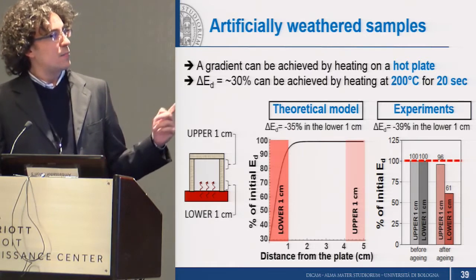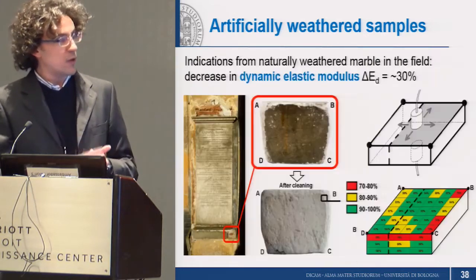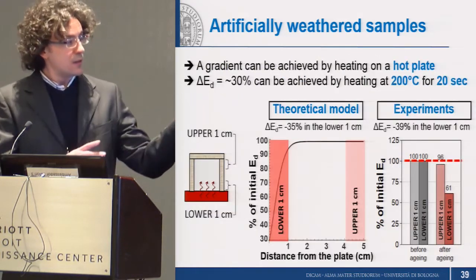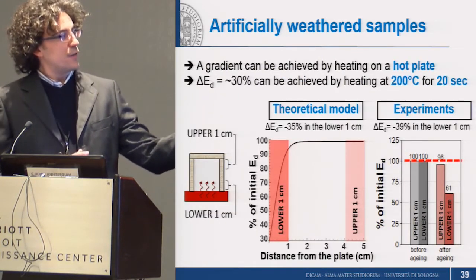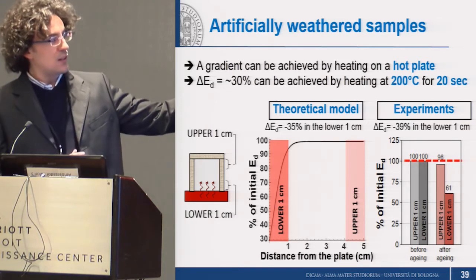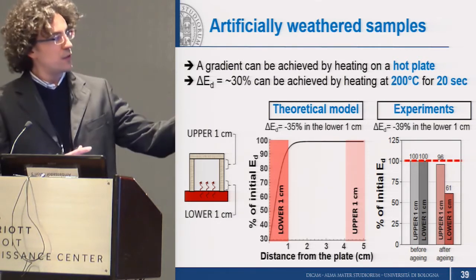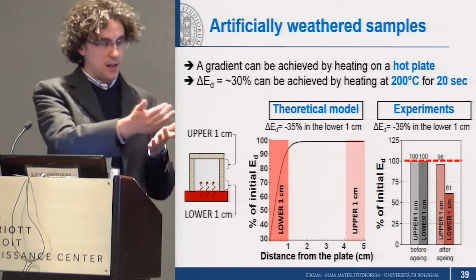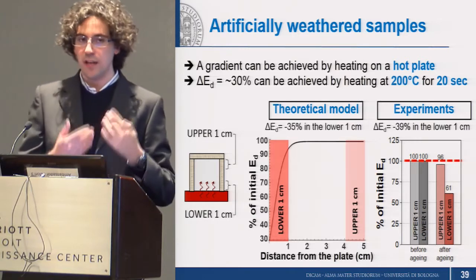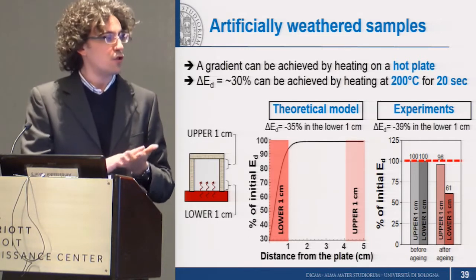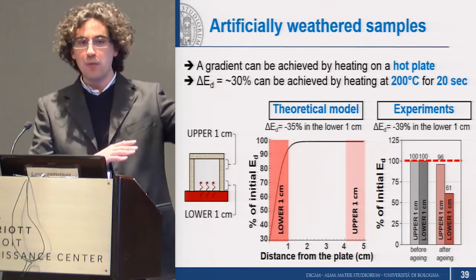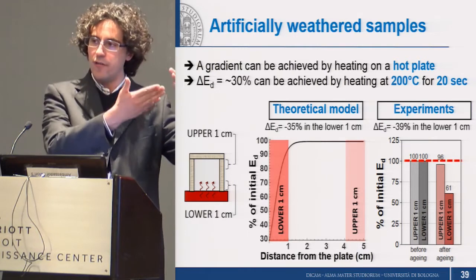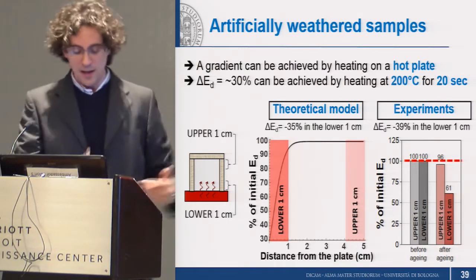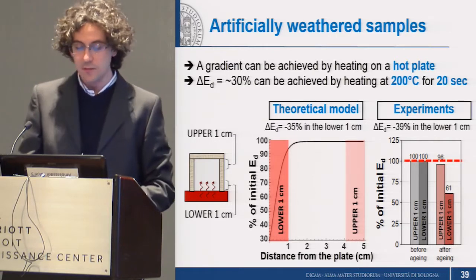So we found out that by heating at 200 degrees for 20 seconds, based on the model, is sufficient to get this decrease in the first centimeter of the stone, leaving the other part undamaged. And this is important because this is the condition in the field, where the marble surface exposed to solar radiation is more decayed, while the underlying parts are still sound.